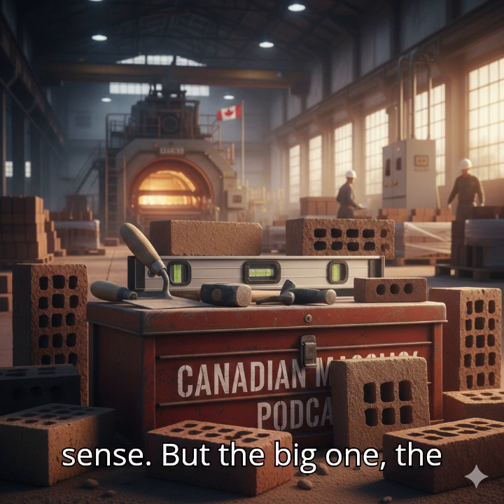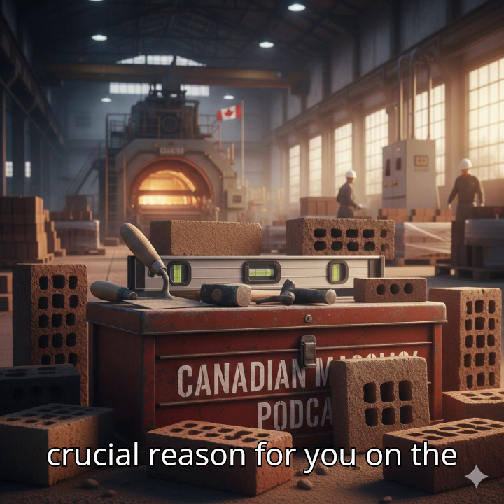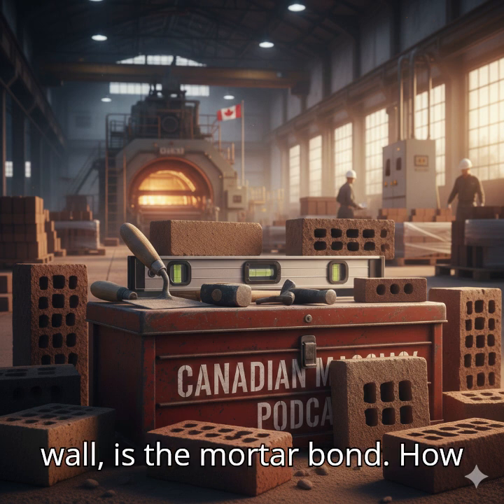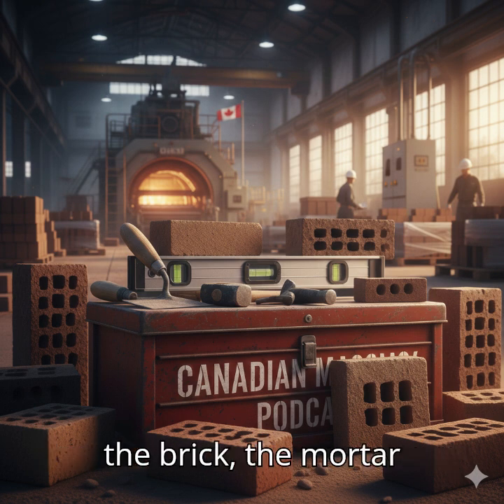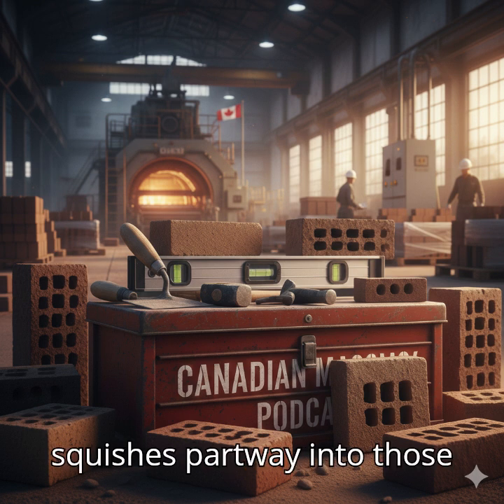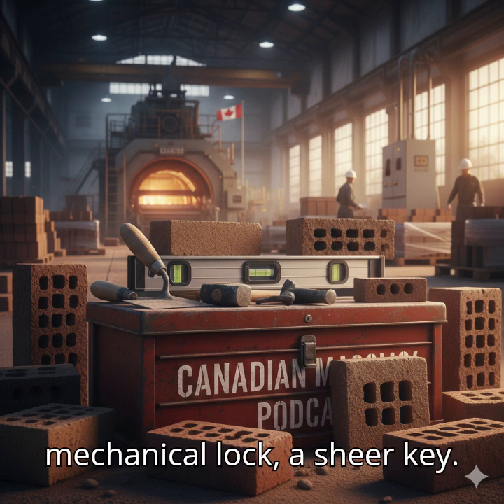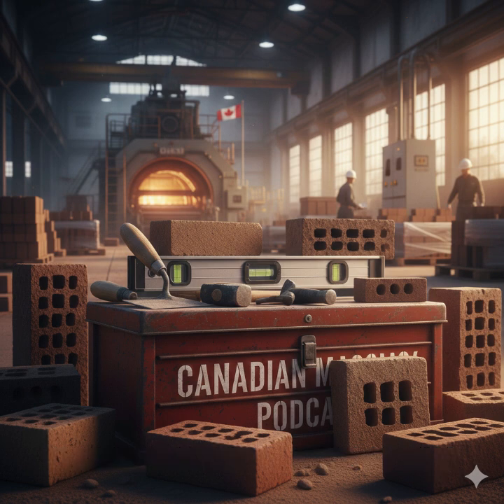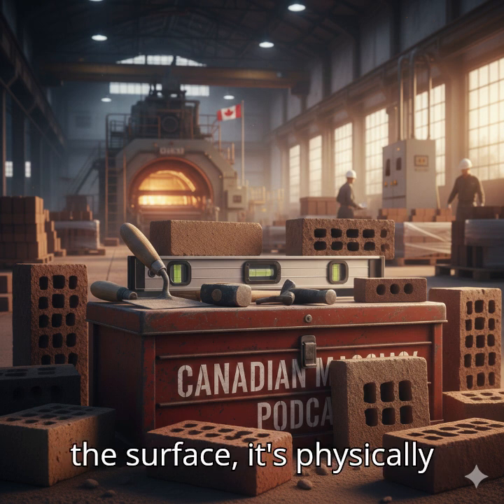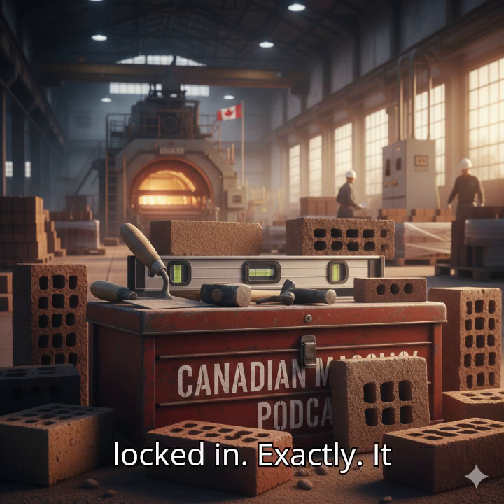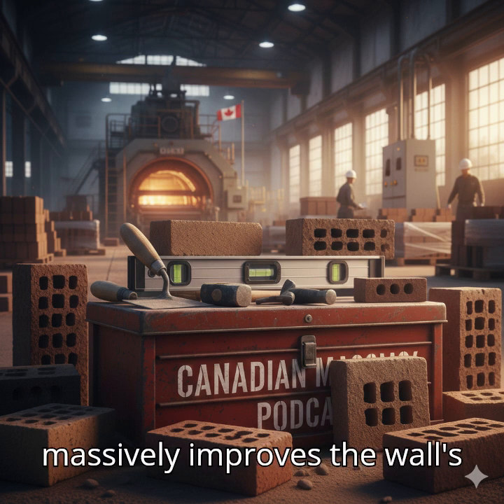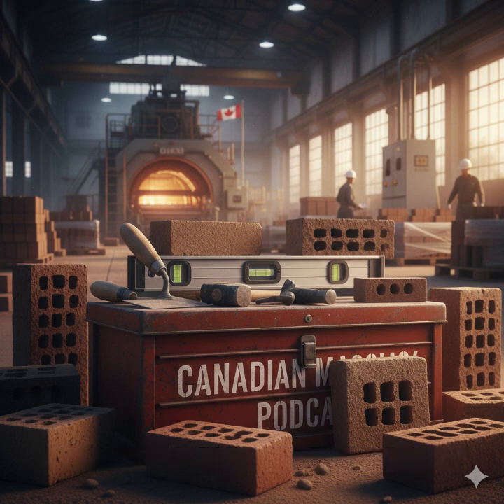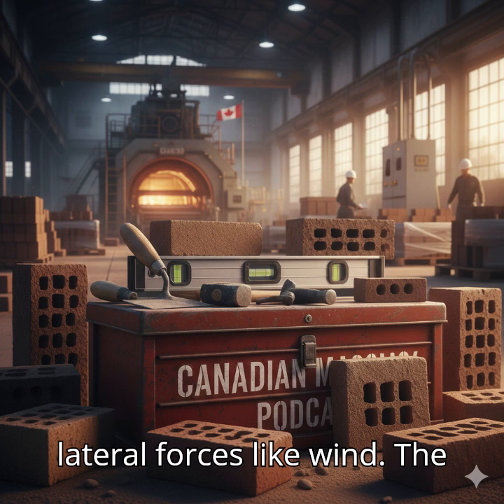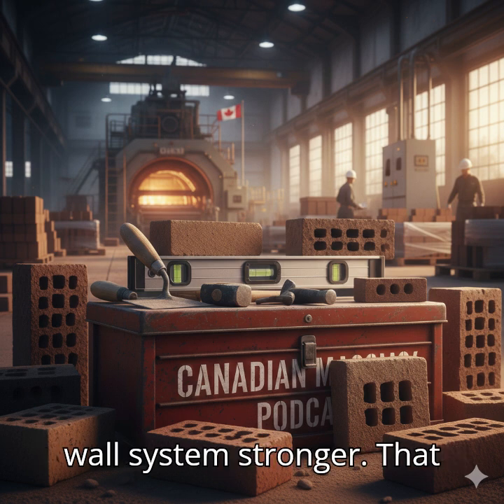Okay, that makes sense. But the big one, the crucial reason for you on the wall, is the mortar bond. How does that work? When you lay the brick, the mortar squishes partway into those cores. It creates a mechanical lock, a shear key. Ah, so it's not just sticking to the surface, it's physically locked in. Exactly. It massively improves the wall's resistance to lateral forces like wind. The cores actually make the whole wall system stronger.